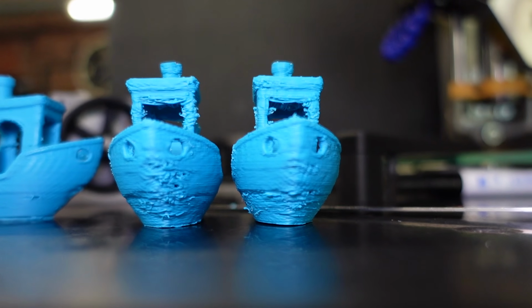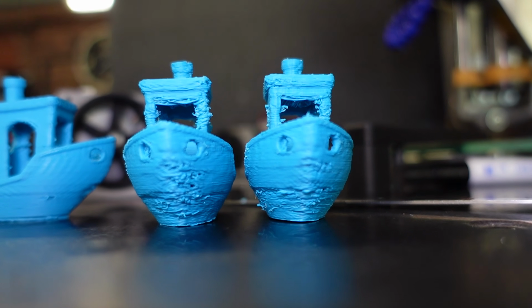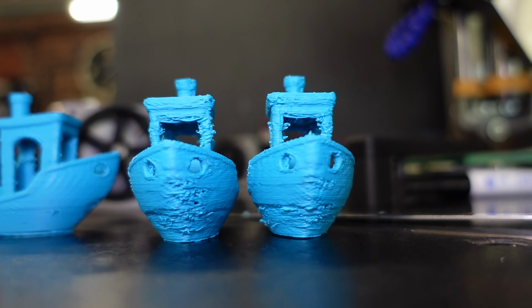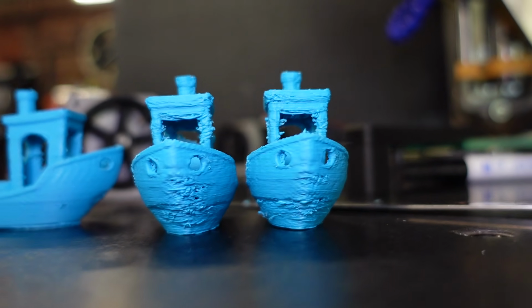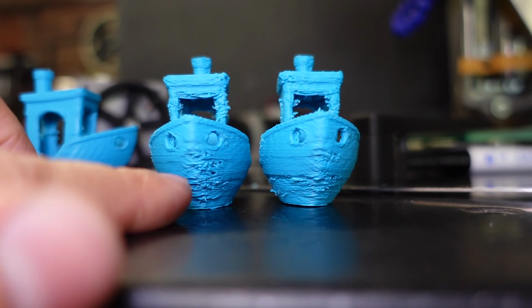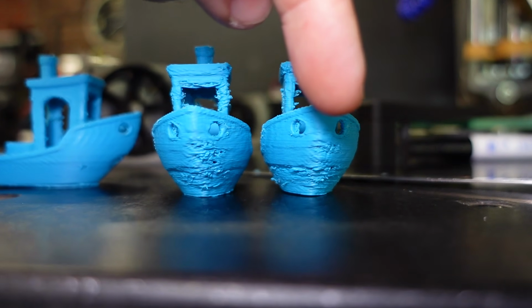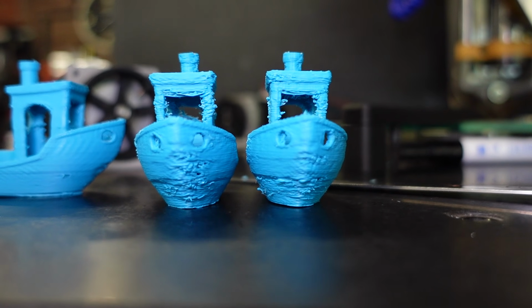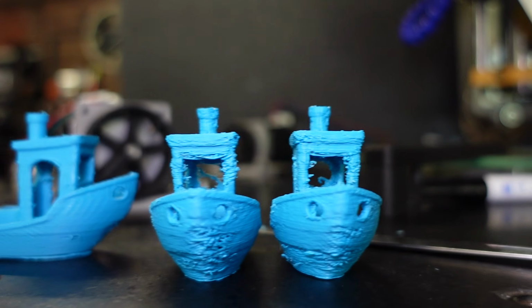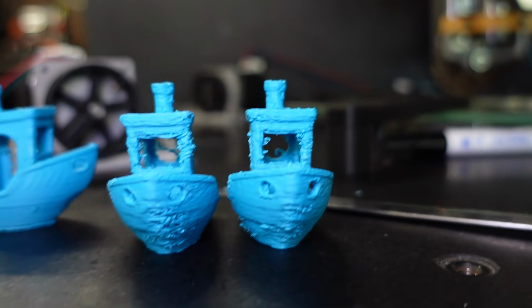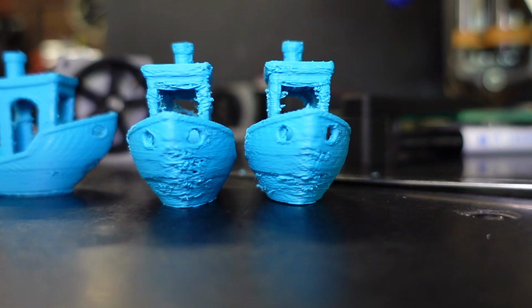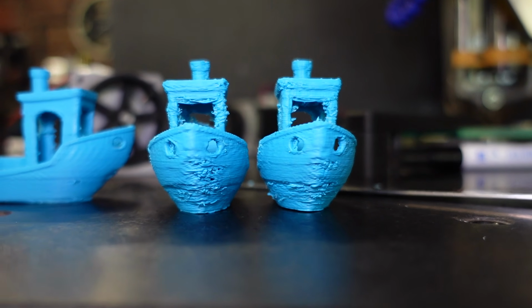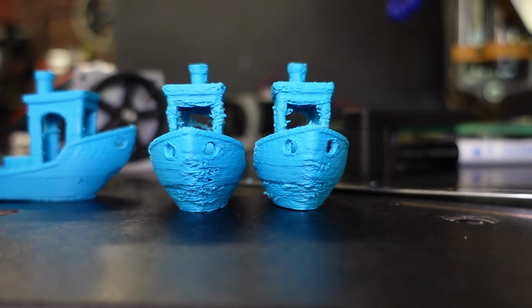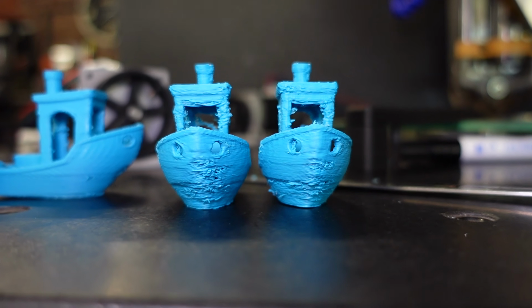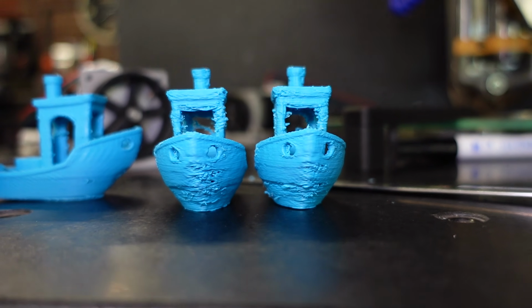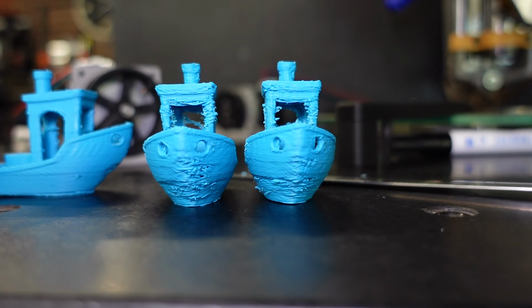So what I wanted to know is, does it scale with the amount of cooling we put there? And the answer is a complete yes. If you have a look at this overhang here, 1 bar to 2 bars, that is definitely an improvement, as well as the overhangs here on top and the chimney. So what this tells me is that all the things we did find out earlier on about adding water vapor or cooling down or cooling media will apply to the ABS.